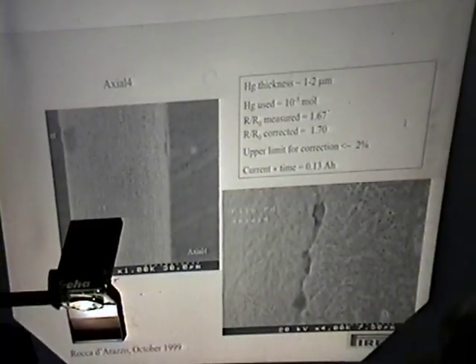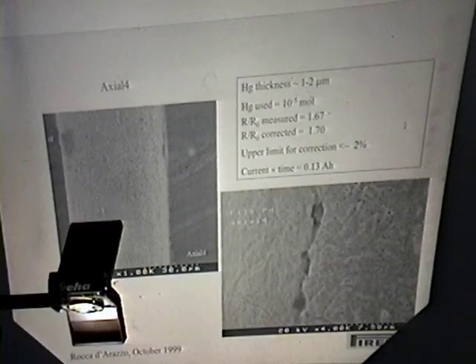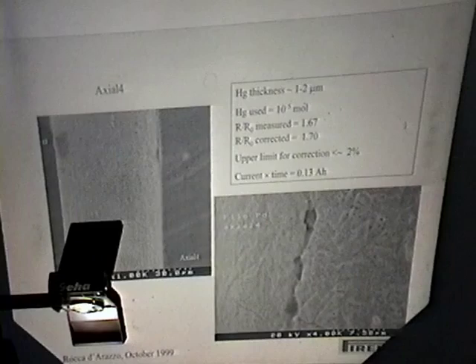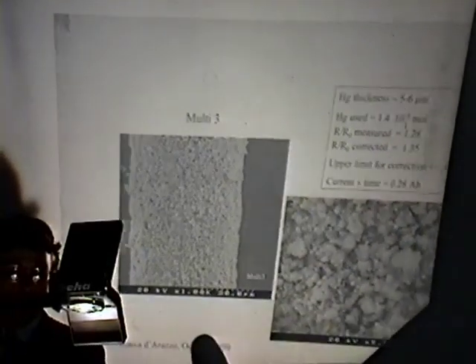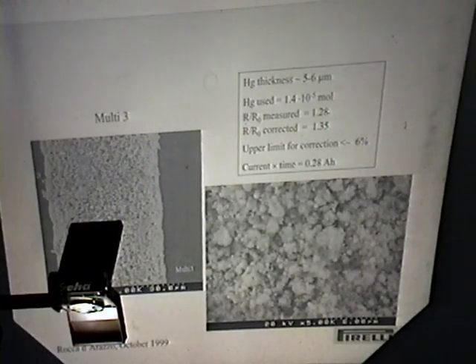I want to show you also some other examples of loaded wire. In this case, we have a thickness of only 1-2 microns, but a worse loading ratio, only about 1.7 of the resistance, and the correction is quite limited, only 2%. This thickness can be controlled by using different mercury quantities, just to give some idea. We used 10 to the minus 5 moles of mercury in our experiment. I show you also a third example with a medium 5-6 microns layer thickness and 1.35 resistance measurement.